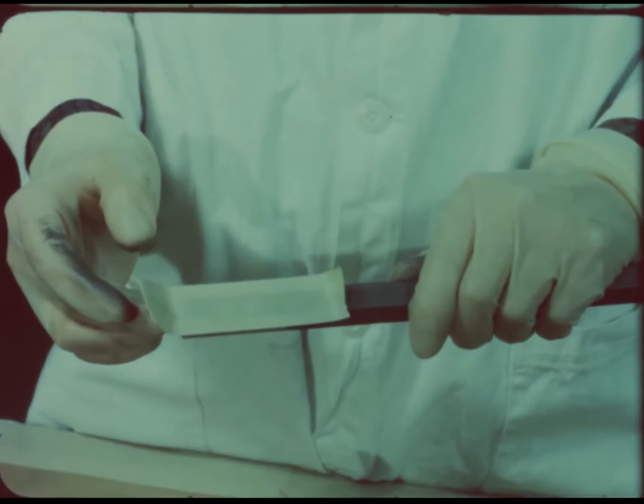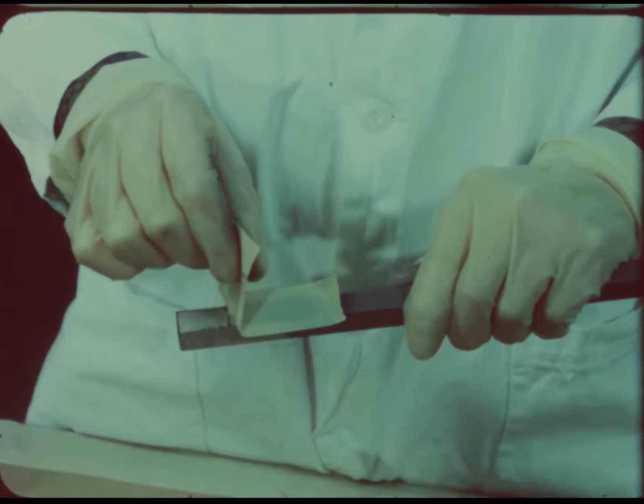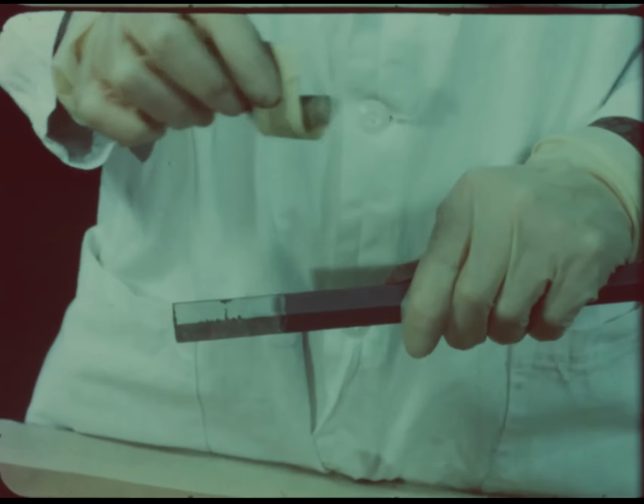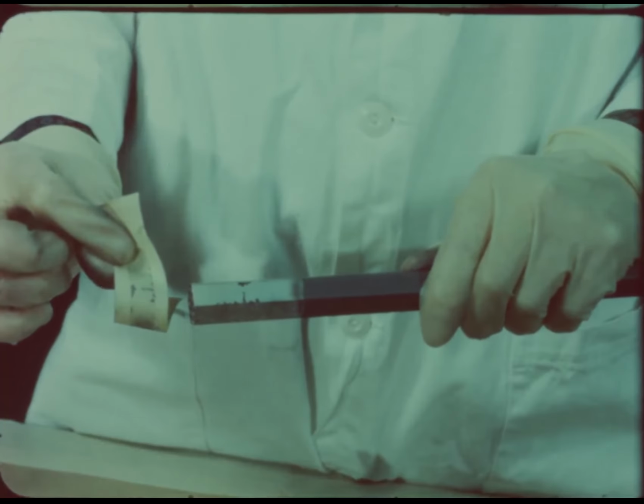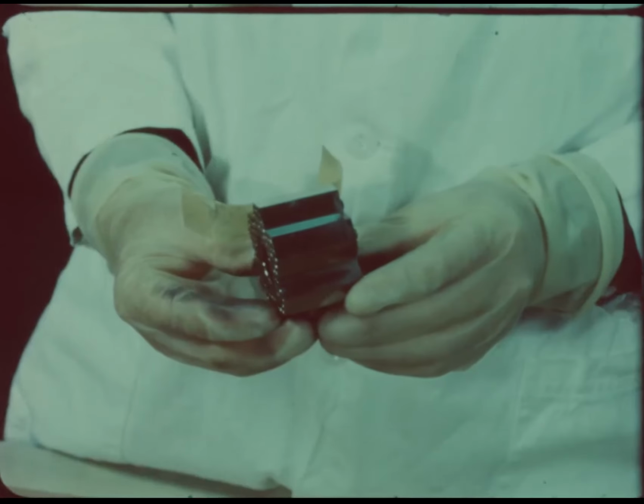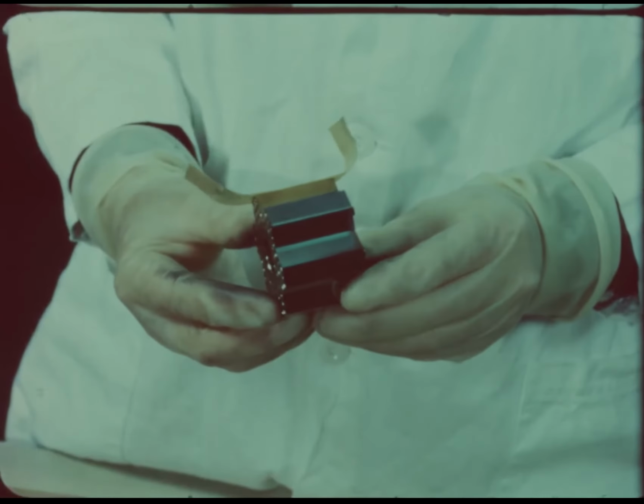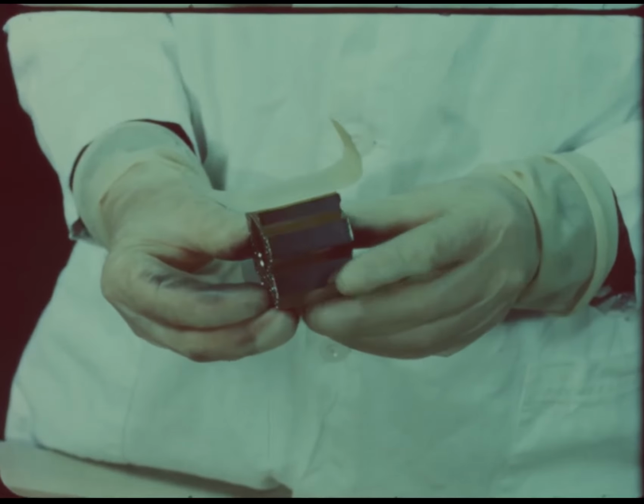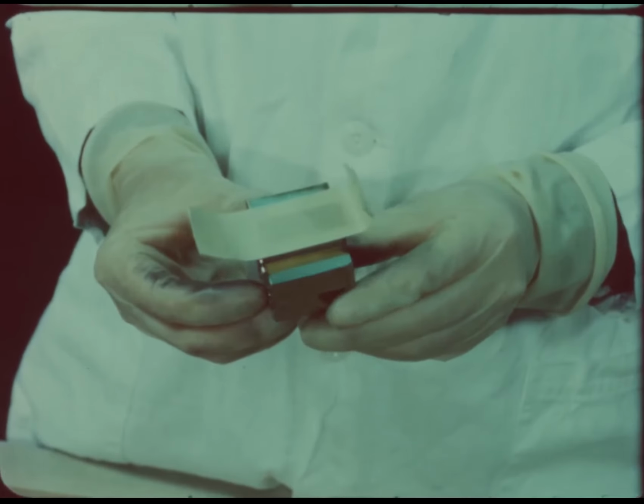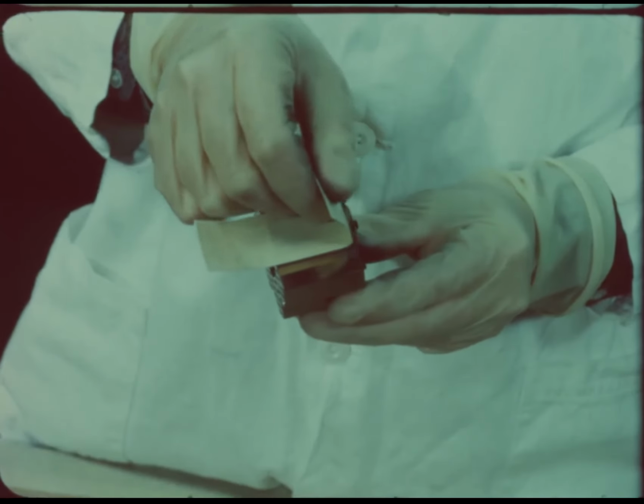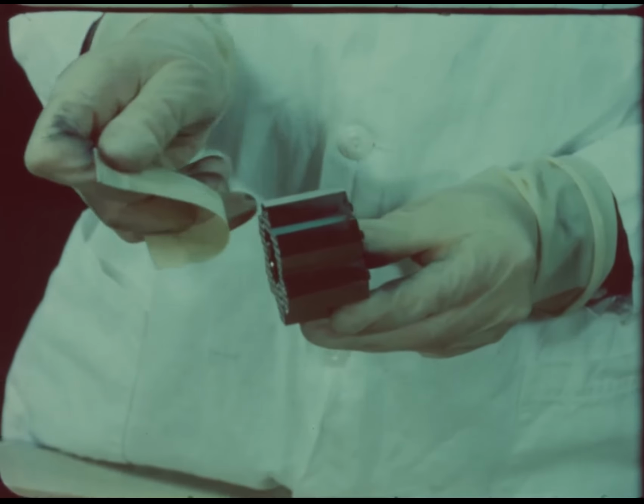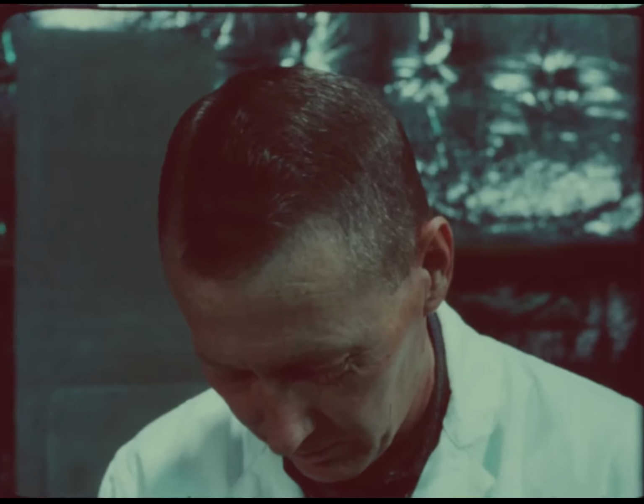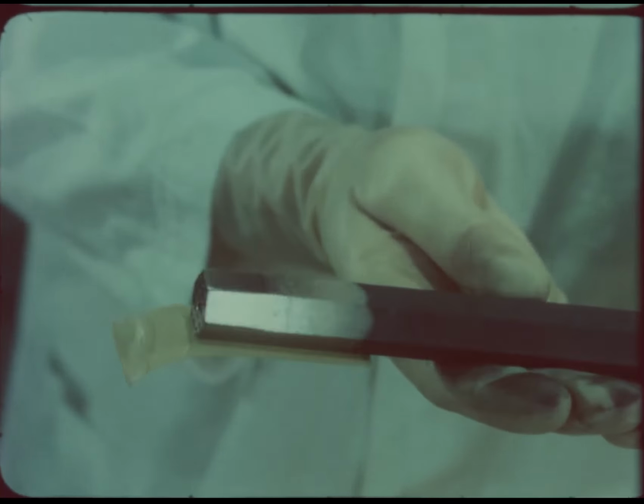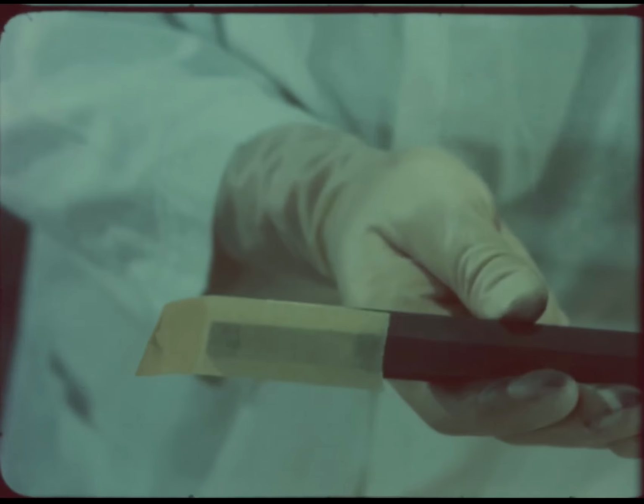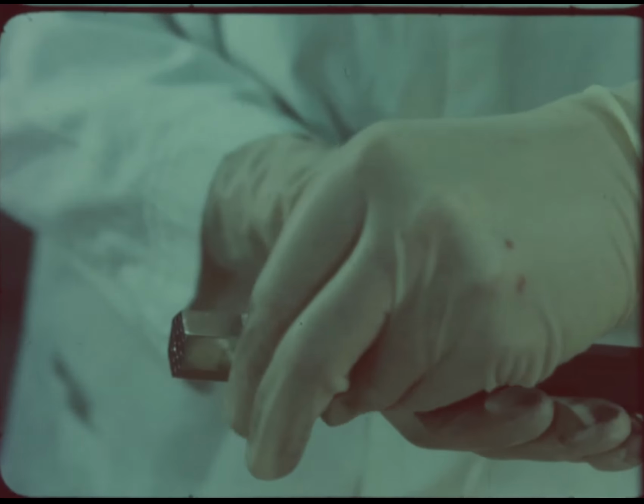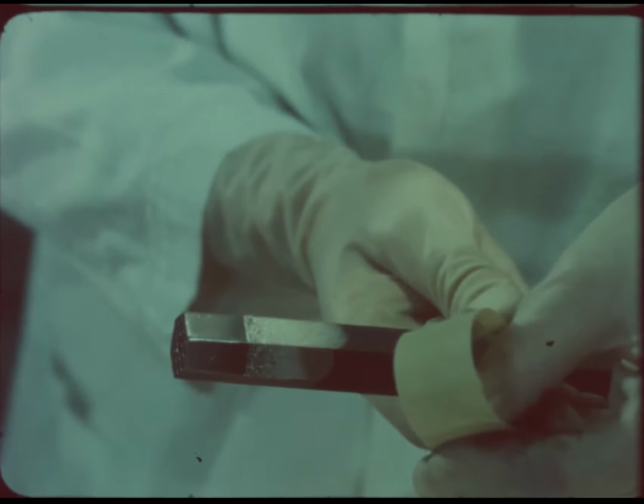The adherence of the coating to the graphite is influenced by many processing factors, and in many cases a firm bond is not established between the two surfaces. It has been found that the coating adheres much better to unloaded graphite, such as this support block, than it does to uranium bead-loaded graphite, as is found in fuel elements. Group CMB3 of the Los Alamos Scientific Laboratory, the group responsible for the coating process, is constantly experimenting with new coating methods, and the results are encouraging.